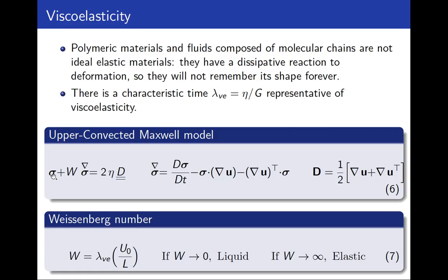But here we have the stress, which is known as the stress tensor, which is a 3 by 3 matrix, with 9 components. And then we have this complex derivative, which measures changes with respect to time and position, and then these other elements that I'm not going to explain for now. But these kinds of derivatives are used to get an accurate representation of viscoelastic behavior.